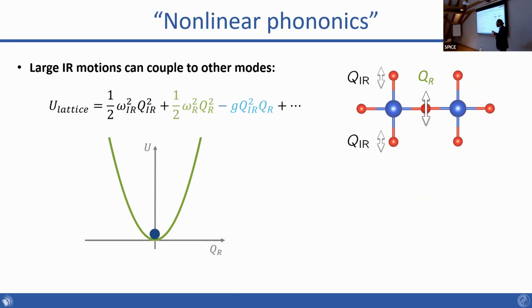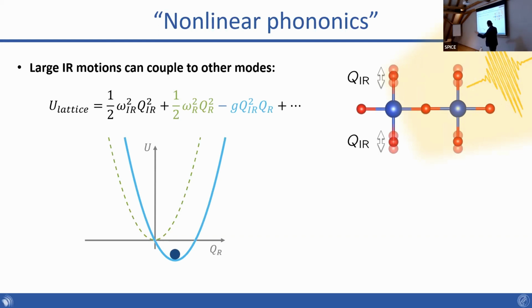So now when I write down the energy of my lattice, I'll have the two harmonic oscillator terms corresponding to these two phonon modes. And the lowest order coupling term between these two that's allowed by symmetry is this one right here, which couples the square of the Q_IR phonon to this Q_R phonon. And so what that means is that when I shine now my laser pulse, which is now bigger, and I excite this Q_IR mode to large amplitudes, you're going to vibrate that mode back and forth. But in addition, through this term, you're going to change the potential corresponding to the Q_R mode. So this is the original potential. And now when I've excited this Q_IR mode, this potential gets displaced. And that means that you're going to now have a lattice that is displaced with respect to the equilibrium coordinate.